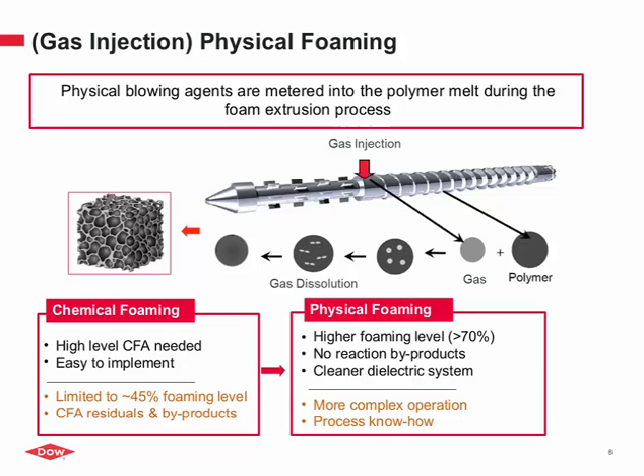So for these high-end, much higher requirements on electrical properties, we prefer physical foaming, and that's what the industry generally practices. With physical foaming, one can reach up to 70 and even higher foaming level. Obviously, there are no reaction byproducts, and it's overall a cleaner dielectric system. However, it comes with its own complexity. It's a more complex operation, quite a bit of control needs to happen. And obviously, it's a process know-how to make this a successful operation.